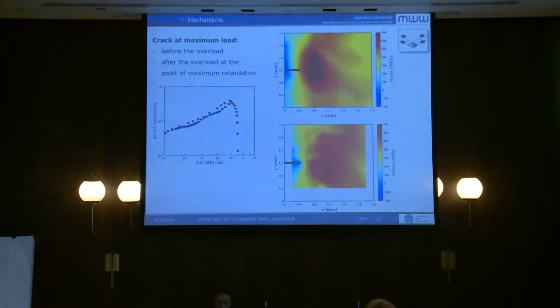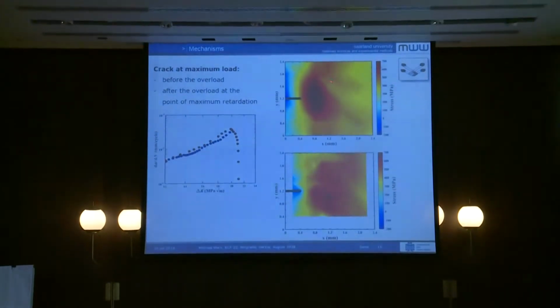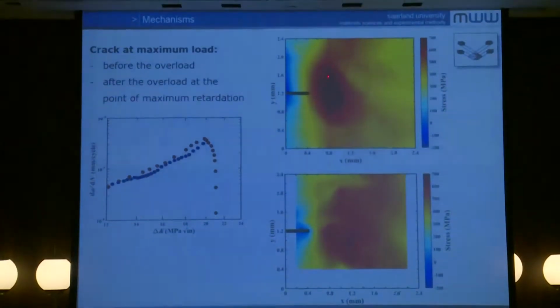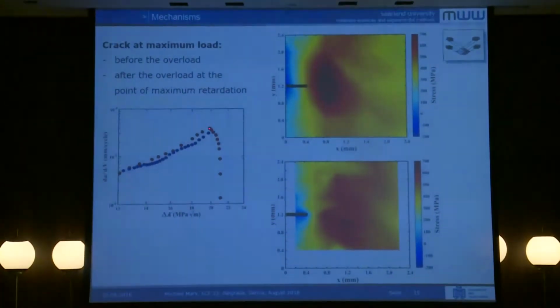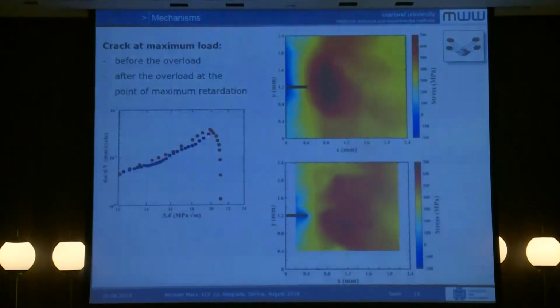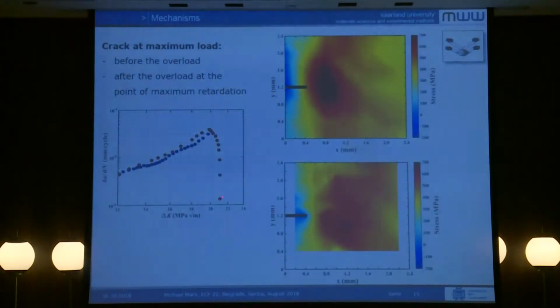So here we have now our measurements from the synchrotron. It's the loaded crack tip at this position before the overload and the loaded crack tip at this position after the overload. And you see that the maximum load in front of the crack tip is reduced, as you would also expect if you take into account the residual stresses working after the overload.